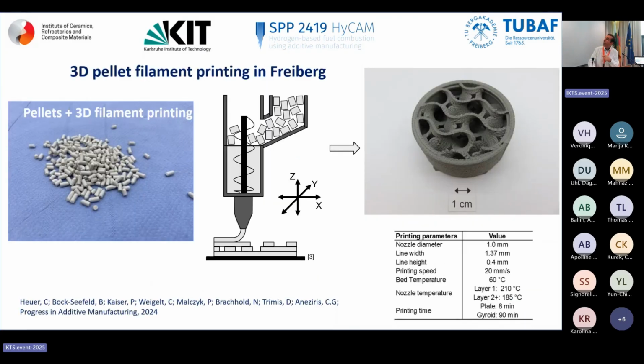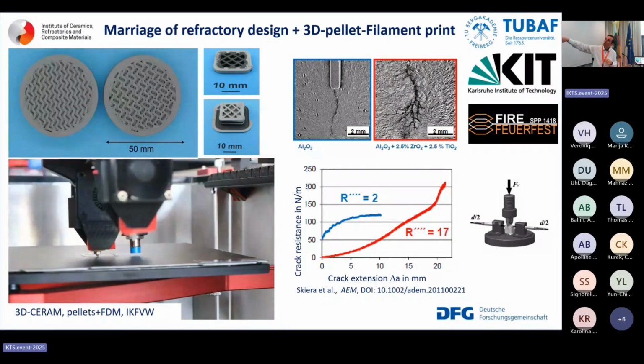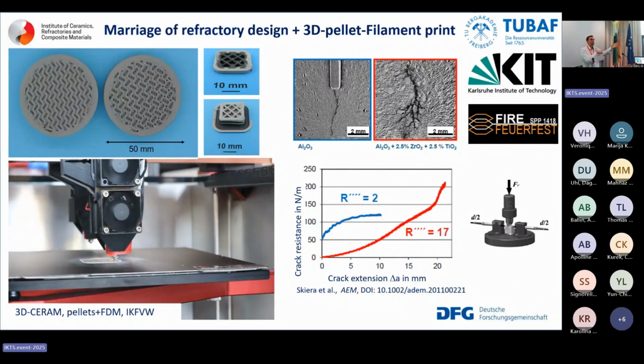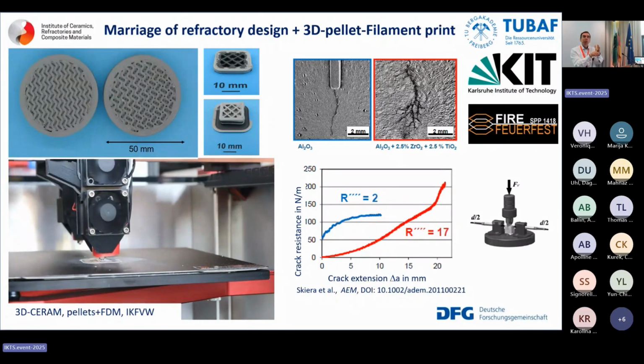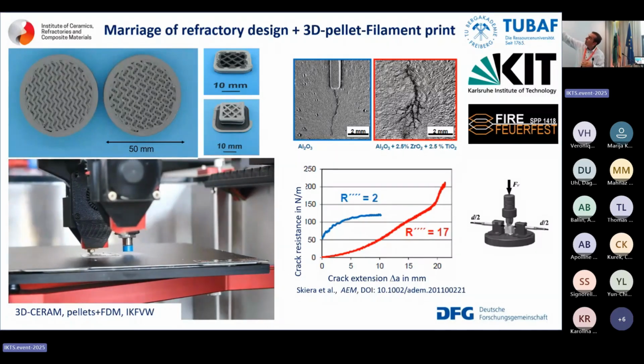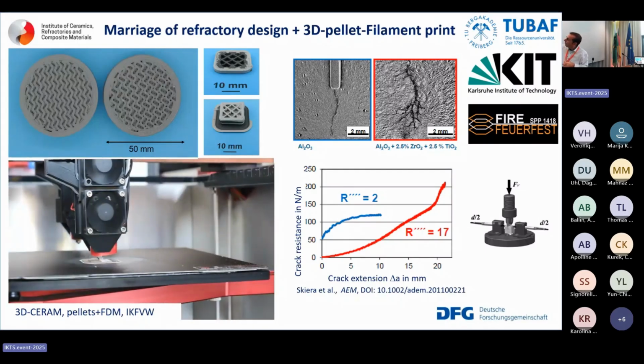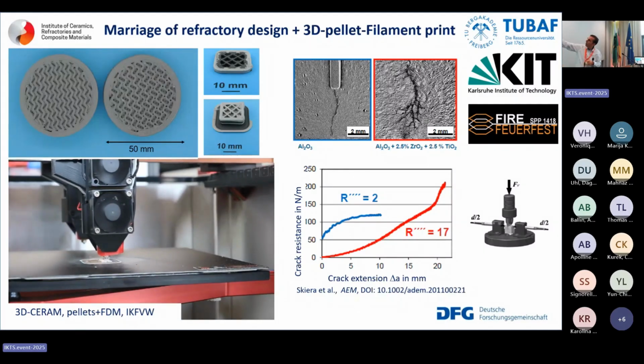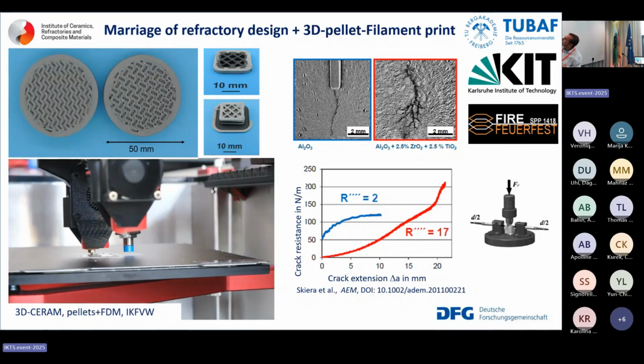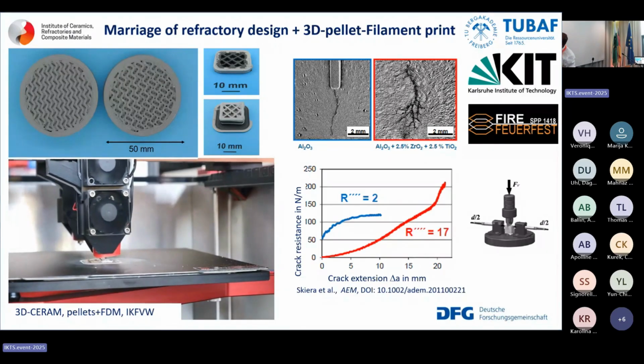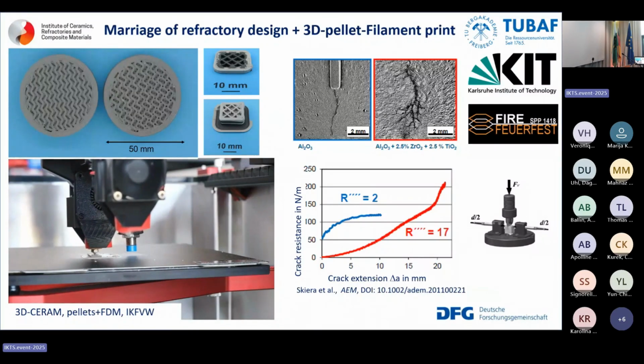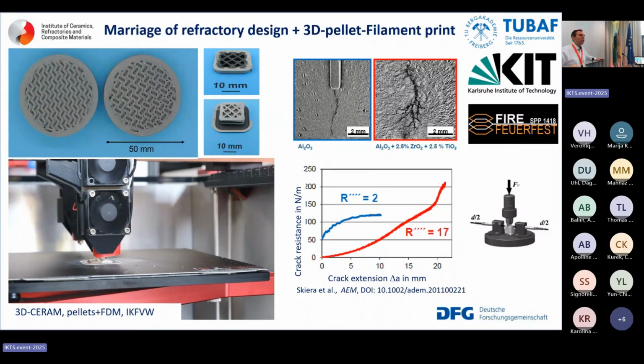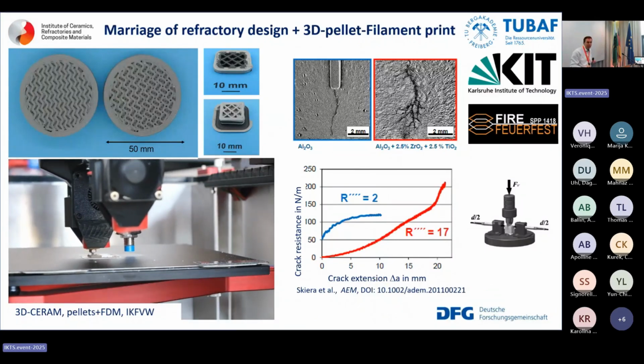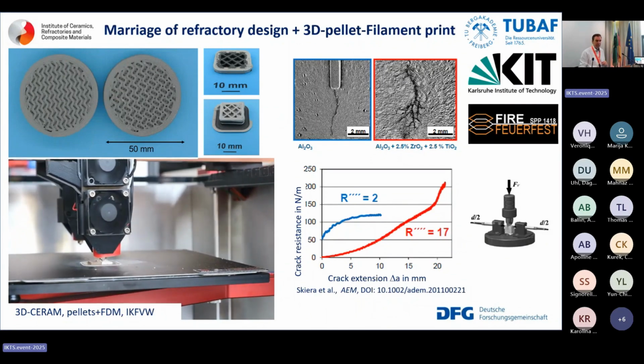Yes, again, you can print, you can pelletize, you can make some kind of gyroidal structures. But of course, you can use also two nozzles. It's going to change because I want to have, for instance, alumina. Alumina is the material, but I want to put silicon carbide in the inside in order to improve the thermal shock performance. Or I want to put an AZT system. And we see here the behavior, the crack resistance of this material, where we have added 2.5 magnesium stabilized zirconia and 2.5 titania. And we see this kind of behavior, not the classical, as we have it in ceramics. So it's like a sponge according to the heat, the mechanical stressing of the material.